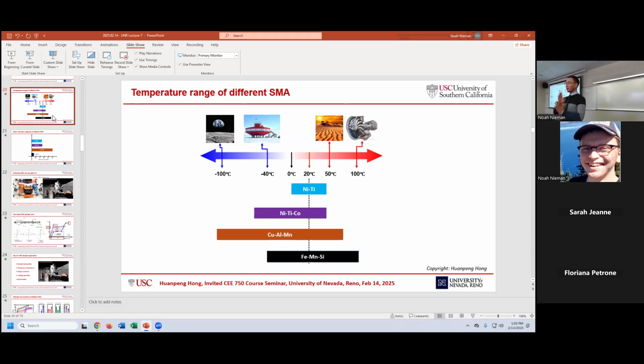Actually, Professor Tazar, there's a few things I want to emphasize on your question. The austenite finish temperature is an intrinsic property of this material. We can control it, but if the manufacturer could lower the nickel titanium alloy to -100 Celsius, they wouldn't even need to develop the copper aluminum manganese alloy. It is controllable, but it is really difficult. For nickel titanium alloy, I think they can lower it to -10 Celsius; I have never seen an AF lower than -10 Celsius. But for nickel titanium cobalt alloy, it is very easy to reach -60 Celsius. Perfect. My point is then you cannot compare beyond their AF. Okay.